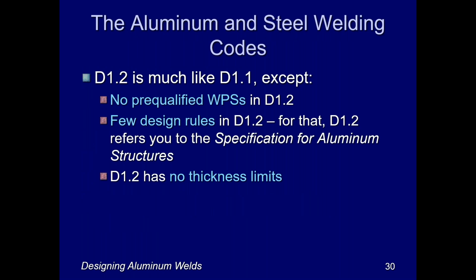Now, a lot of people are familiar, if they're familiar at all, with AWS structural welding codes with D1.1 because D1.1 came before D1.2, and it's the steel welding code. And a lot of people that are familiar with D1.1 want to know, well, what's different about D1.2, just for a point of reference. And I think that's a handy way to look at things here. And there are some fundamental differences. One, there are no pre-qualified weld procedure specifications in D1.2. You have to qualify every procedure that you use. And that's a big difference.